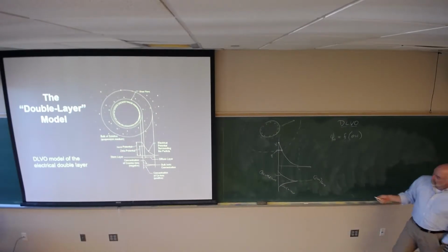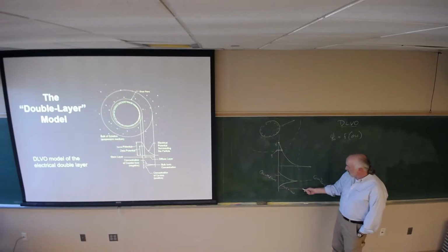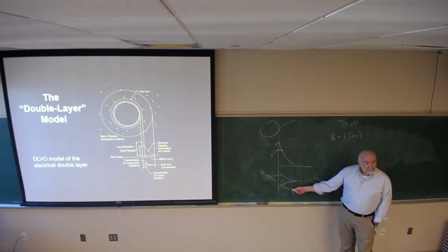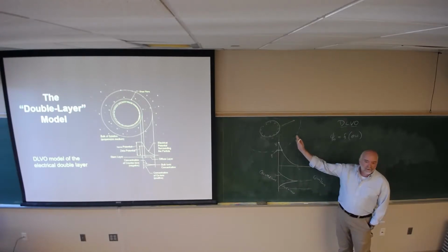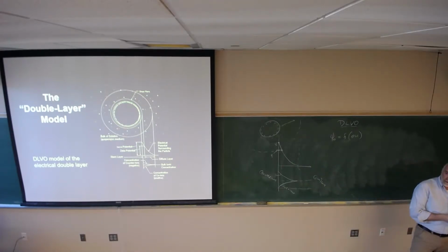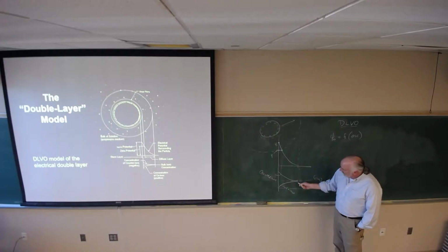And then coions. What you have here, you would argue that you have no ions at the surface of the particle which are similarly charged to the particle surface. So you could argue that this is essentially 0. And then you would segregate charge as you move into that diffuse layer to allow ions which are oppositely charged to be pulled to the particle surface and ions which are similarly charged to be pushed away. So we have this decay function for ions, and where that gets back to the bulk ionic concentration, wherever that segregation ends, is the thickness of our double layer.